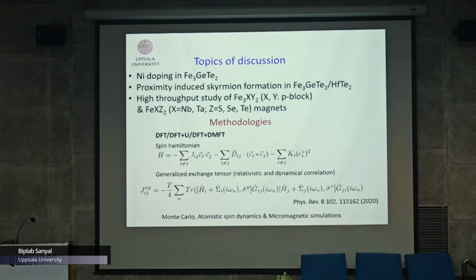A spin Hamiltonian can be very long. The essential spin Hamiltonian that we usually use is given here, the isotropic part, where the parameters that we calculate from DFT calculations, DFT or beyond, are these Jij parameters, pair exchange parameters. The Dzyaloshinskii-Moriya interaction parameters, we also extract from ab initio. And then the anisotropy parameter Ki, that is also very important.